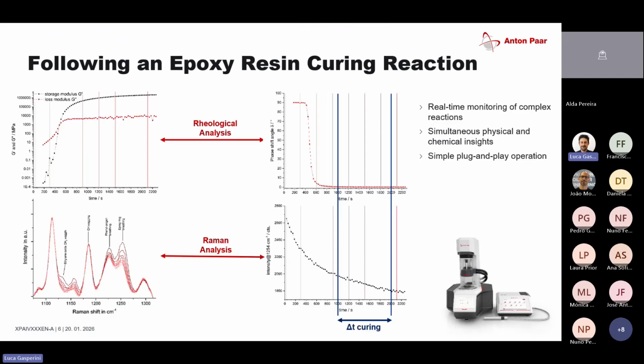So I know that that's a lot of information. So just focus on the top here. We are taking a look only on the physical characterization, on the rheology. So the black line corresponds with the storage modulus, so how elastic is my sample, and the red line here corresponds with the loss modulus, so how viscous is my sample? And what we were observing here was a curing process. So we placed a two component material onto the rheometer, and then we were measuring it at a certain heat and a certain shear rate.